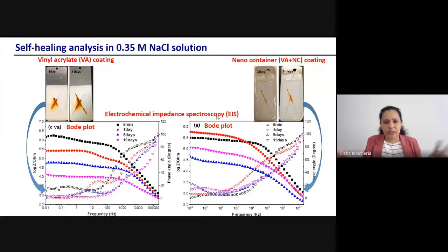EIS spectra we can plot in two methods, Bode plot and Nyquist plot. I'm giving here the Bode plot. This is a little bit complicated, but if you look on the Bode plot, the first thing you can understand is impedance. This Y1 axis is the impedance. What is impedance? Impedance means resistance, the resistance that the coating gives towards the corrosion reaction. So the impedance of the pure vinyl coating is continuously decreased. But in the case of nano container coating, it decreased till 9 days, but after that it started to increase. So this is the behavior of the self-healing coating.